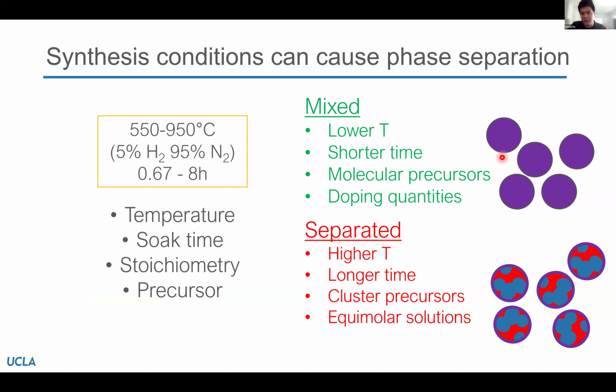So what I'm showing in a cartoon here is this purple would represent a well-mixed solid solution of molybdenum and tungsten, where at each lattice site you have an equal probability of having molybdenum or tungsten, versus a case where, although the particle on its own through bulk methods might look like a solid solution of molybdenum and tungsten, we actually have small nano domains of pure molybdenum or molybdenum-enriched domains, as well as tungsten-enriched domains. And so we understand now that despite being able to achieve this phase at various conditions, there are certain synthesis kinetic considerations that allow you to have more mixed or more separated solid solutions.